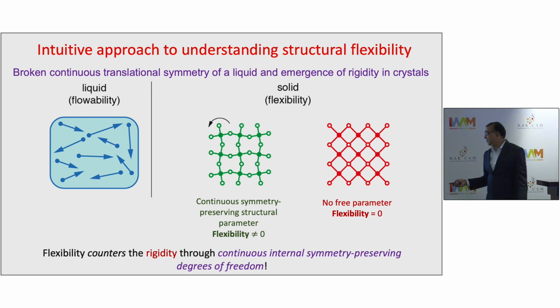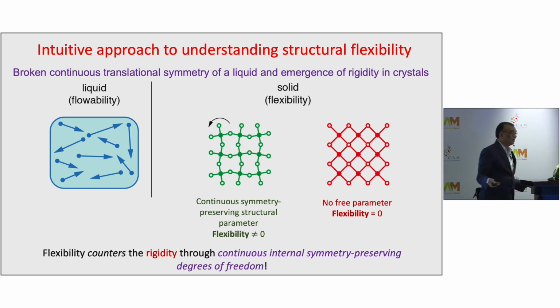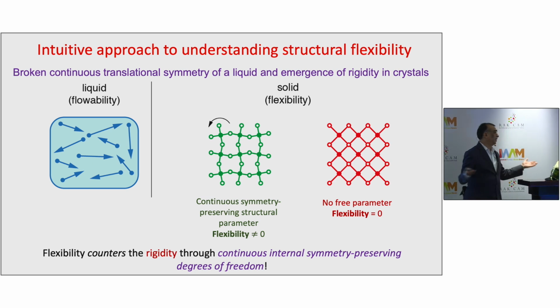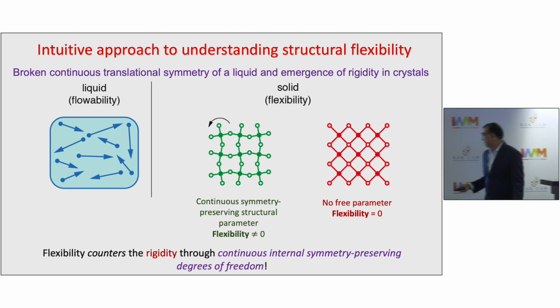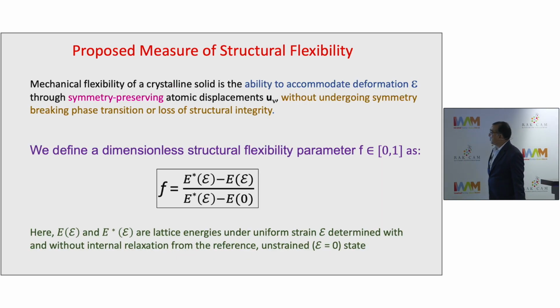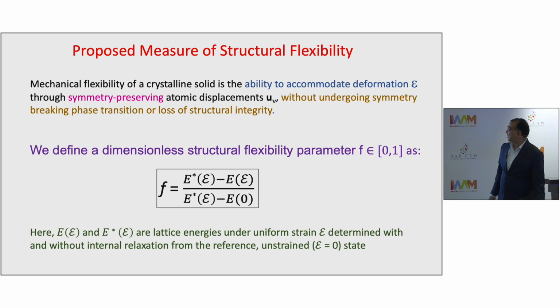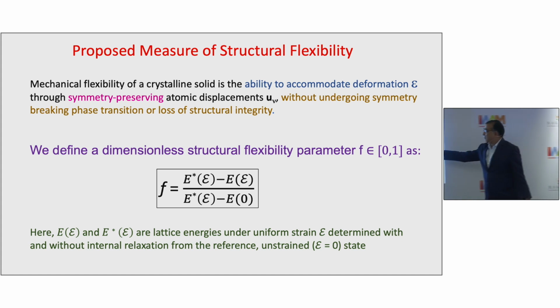So flexibility in a way counters rigidity. Rigidity is a consequence of broken continuous symmetry, and in our notion, flexibility tries to reduce that rigidity to 0 if you go to the infinite limit, to a liquid in some sense. Okay, so let's look at our measure of flexibility. It is basically the ability to accommodate deformation epsilon, the strain in the system, through symmetry-preserving atomic displacements, without undergoing phase transition or integrity loss. So our parameter is defined here.